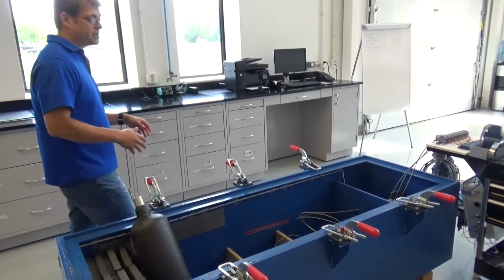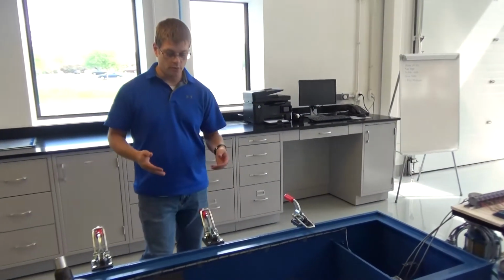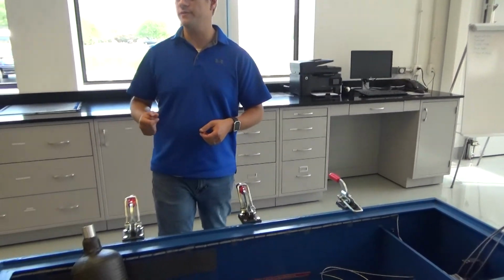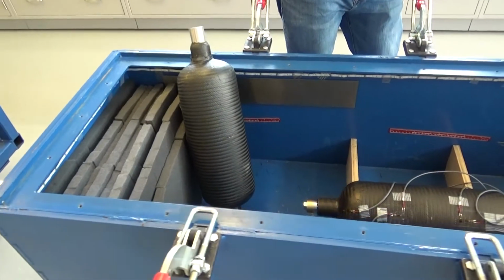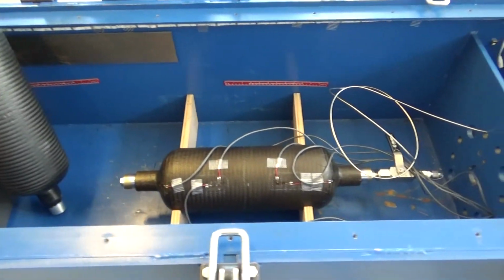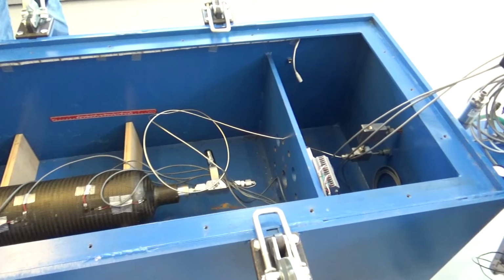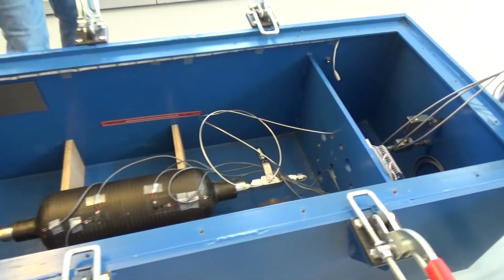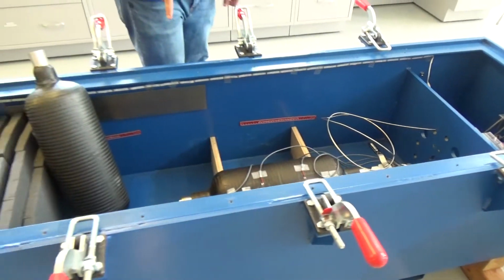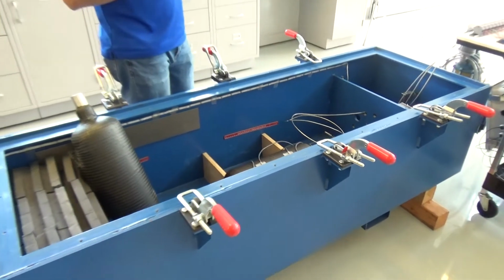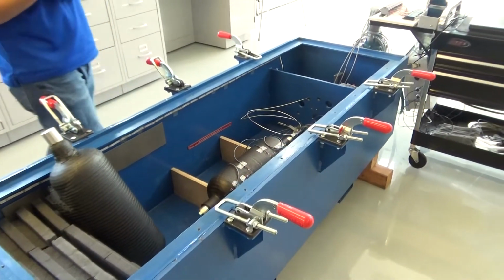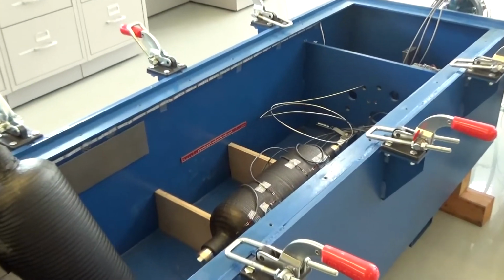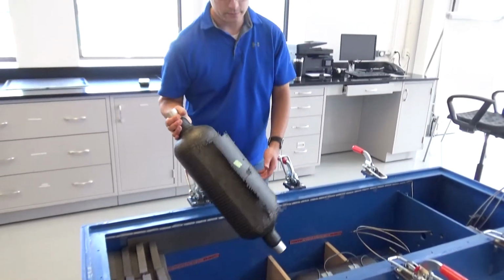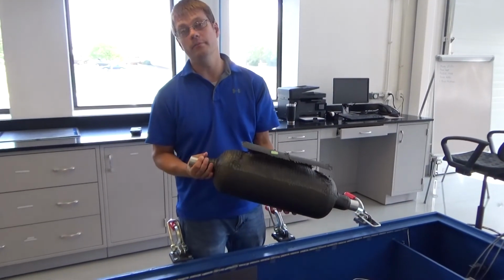Here's another great example of a testing apparatus that we made. This really shows how we can make the fabric, wrap a pressure vessel, mold a pressure vessel, and then test a pressure vessel. This burst chamber is capable of producing 30,000 PSI using water. And on it here you can see that we have multiple strain gauges ready to record the different strains and movements of the tank during testing. Here's an example of a braided tank that has already been burst.